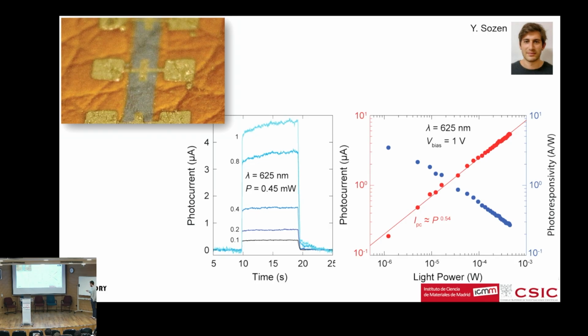So we get really fast responses, in comparison to other molybdenum disulfide photodetectors, though they are not the fastest by far. Molybdenum disulfide is relatively slow. What is important is that the responsivity of these devices reaches more than 1 ampere per watt. Figures of merit are important in order to compare different technologies. If you don't have figures of merit, you cannot compare two devices fabricated with different material platforms, different technologies.